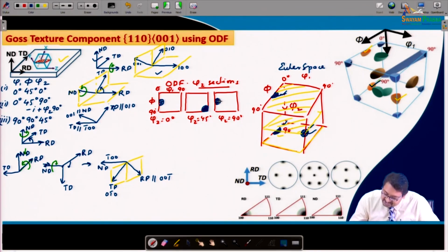are already discussed. In terms of the pole figure, here we have shown, to compare for you, the positions for the 100 poles, and you can see that it shows a two-fold symmetry, because the ND is here and the ND is 110, which has a two-fold symmetry. You can see the 110 poles too, where at the center we can see the position 110 as ND, and here is the 111 pole figure. So, one can observe from all these pole figures a two-fold symmetry.